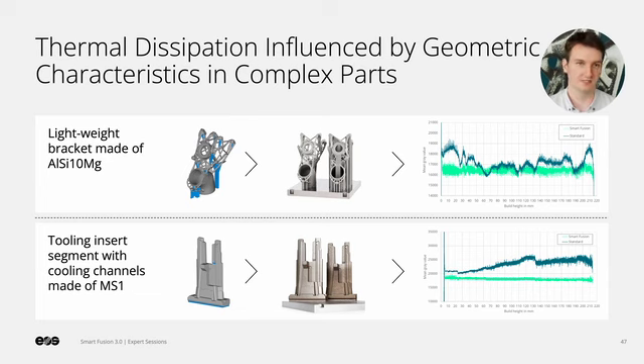Thermal history can be even more complex in real parts. For the lightweight AlSi10Mg bracket, for example, the mean gray value fluctuates due to the drastic changes in geometry and the exposure area over the build height. Bulky sections such as the ring geometry near the top of the part, as well as the overhang areas, generate regions where the OT signal is elevated. Actually, the ring geometry is clearly visible as a plateau of higher gray values from about 130 to 180 mm build height.